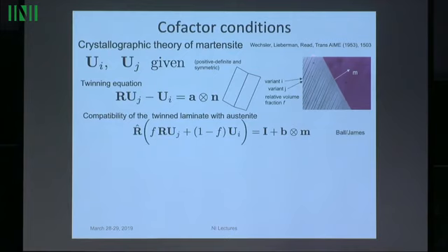It's between a more delocalized bulk elastic energy, which extends over a much larger region, and interfacial energy on these bands. In some scaling regimes the branching is preferred, and apparently it's preferred in this material because we do see the branching. It's not so uncommon, but we don't always see it, of course.